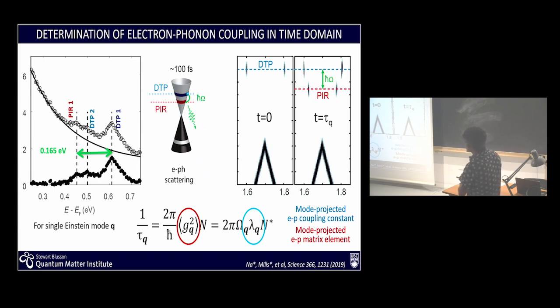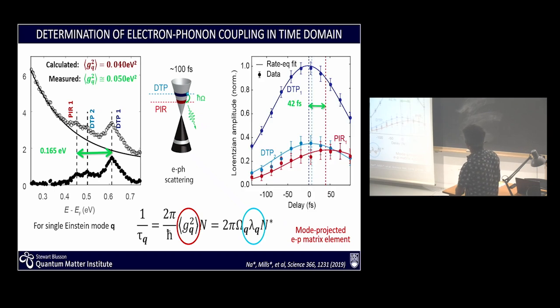And so now you just watch, over time, by doing a pump and probe experiment, how the intensity transfers from this main peak to the phonon replica in the spectrum. And you can see that very clearly as a function of delay. Now if you have, in addition to the energy resolution to resolve the structure, also the temporal resolution, you can see that 2 of these transitions in blue, the optical ones, are peaking at 0 delay. That's when you have the highest probability of pumping into those unoccupied states. The phonon replica in red here comes up with a delay of about 50 femtoseconds. And so that is the time that it takes for the electron to scatter with the phonon and populate the state here.